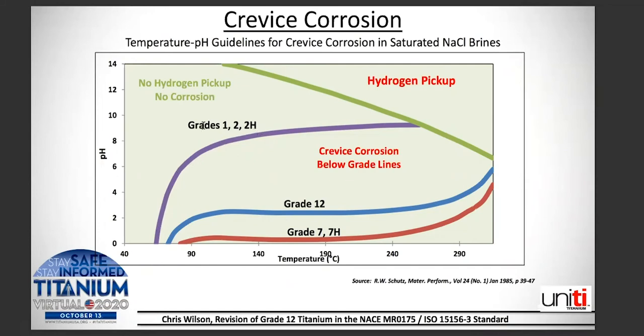Anywhere above this line, if the pH is more basic, you will result in no hydrogen pickup, no corrosion. However, if you fall below that purple line, then there's a potential for crevice corrosion below the grade lines. So if you're in a more acidic environment at a higher temperature, grade 12 may be an option for you. Down around pH levels of 3 and above, grade 12 could be a viable alternative.